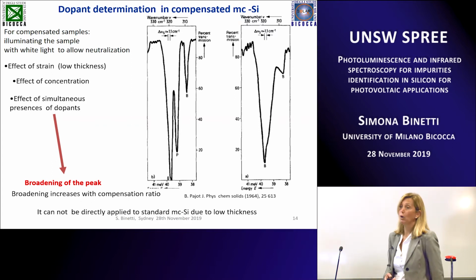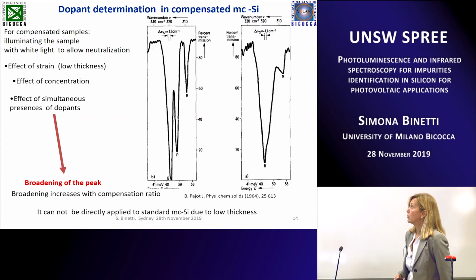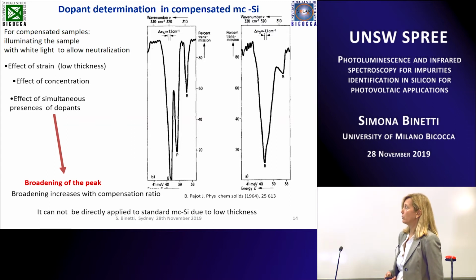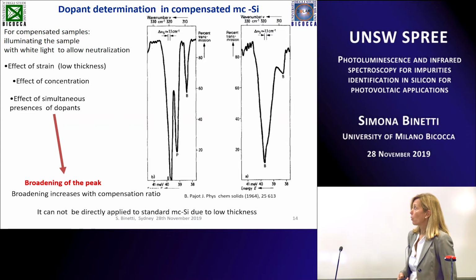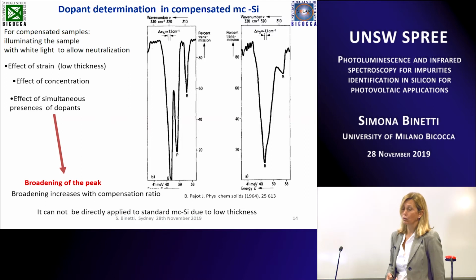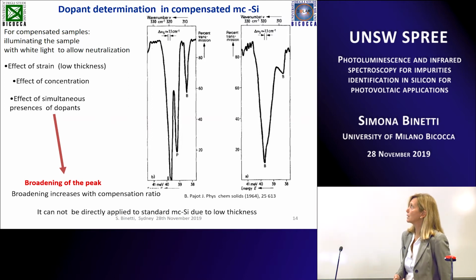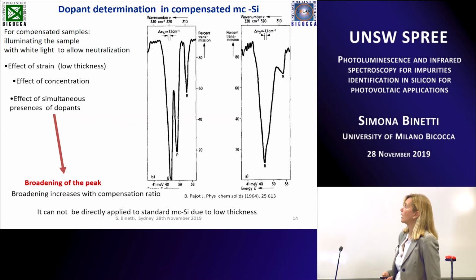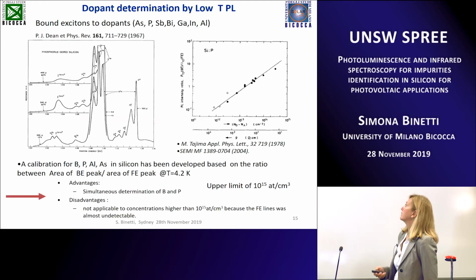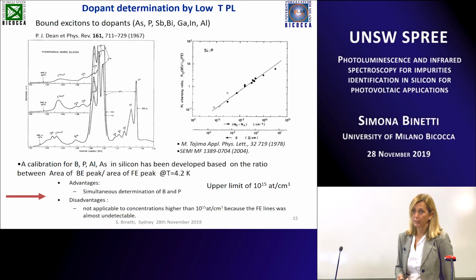you have usually low thickness, so you can have a strain, or you can have also the simultaneous presence of dopants that can cause a broadening of the peak, and this broadening increases with compensation ratio. So it's not always simple to detect dopants in compensated multicrystalline silicon, like in the case of monocrystalline one. But in this case, you can use photoluminescence.